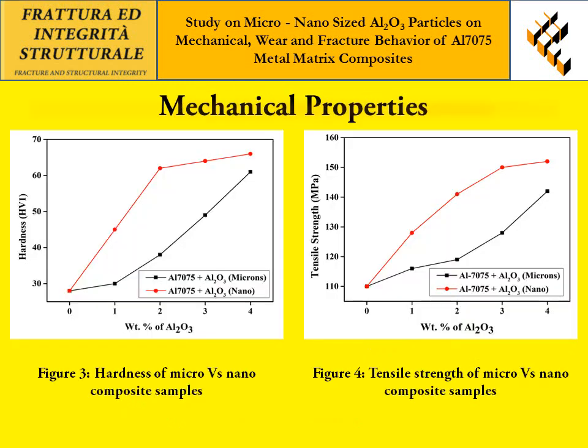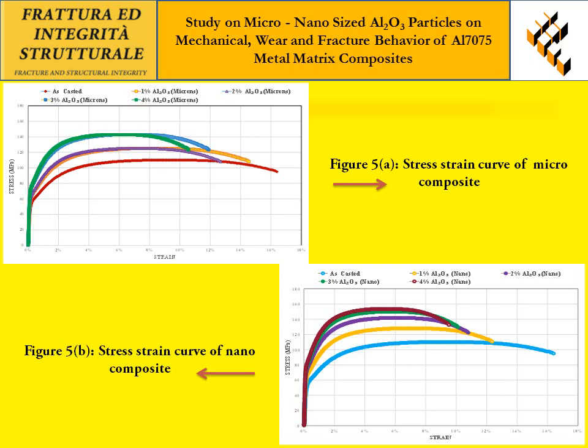Figures 3 and 4 show the hardness and tensile strength of micro versus nano composite samples. From the outcome, it is observed that composites and nanocomposites exhibit better mechanical properties compared to the base matrix. It is also observed that nano-sized Al2O3 particulate reinforced composites exhibit better mechanical properties compared to micro-sized Al2O3 particulate reinforced composites. Figures 5a and 5b show the stress strain curve for the micro and nano composites. It is observed that the base alloy has the highest plastic strain and also exhibits the least resistance to plastic deformation.